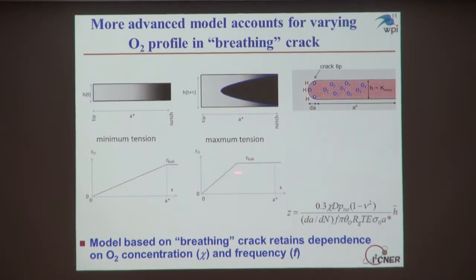And so the oxygen distribution profile is actually fluctuating between these two types of distributions as the crack opens and closes. But when you work through the math, we essentially find a model formulation that's no different than the previous one, and the only difference is that we have to consider essentially a time-averaged crack opening. But this is very comforting that there's the same dependence on critical variables like the bulk oxygen concentration, the load cycle frequency, and the mechanical crack growth rate. So for now, we're sticking with the simple model.